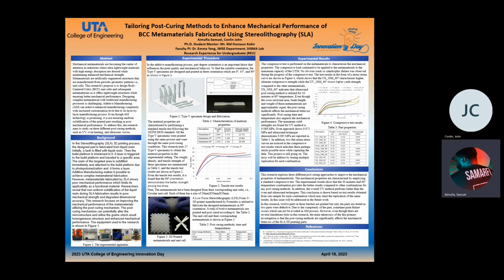The material properties are characterized by performing standard tensile tests following the ASTM standards. All the type V specimens were printed using the same processes and went through the same post-curing conditions. This research tested at least 27 type V specimens to obtain the mechanical properties in the experimental setting. The weight, density, and tensile strength of the specimens are summarized in Table 1. The tensile test results are shown in Figure 2, and from them it is found that the 90-degree orientation demonstrates the best strength among the three orientations.